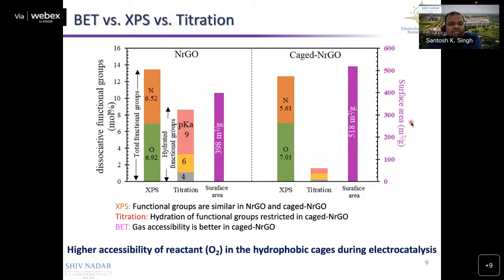So when we compare the BET surface area, XPS, and titration, we can see from the XPS analysis that the nitrogen amount and the oxygen functional groups are almost similar in both the hydrophilic and hydrophobic cases. However, from the Boehm titration, we have seen that the amount of functional groups getting hydrated during the titration is higher in the hydrophilic case, and lower in the hydrophobic case.